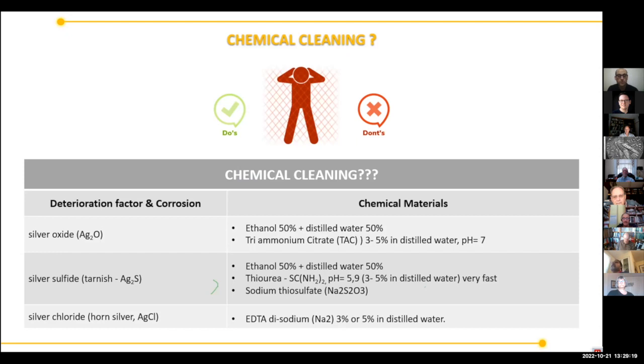for ancient coins, you must take many cautionary measures into account. You have to start with low concentration, and stop before reaching the original surface and middle core. Never leave your coin in a chemical bath without supervision or overnight. Check the pH of the last bath on the surface of your coin. At the end, after finishing the chemical cleaning process, rinse and dry your coins at least 3 times, each one for 1 hour minimum. The use of different chemical cleaning materials depends on the types of corrosion products that the coins contain, as shown in this table.